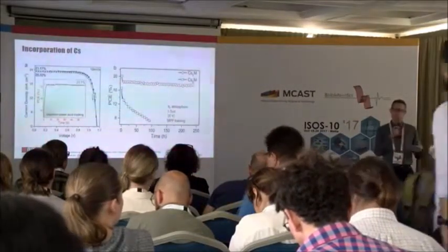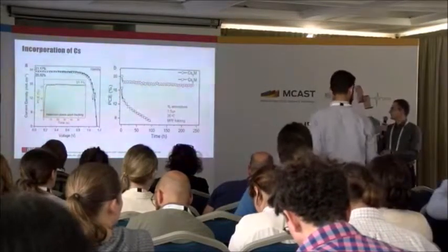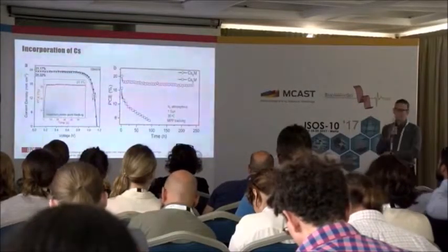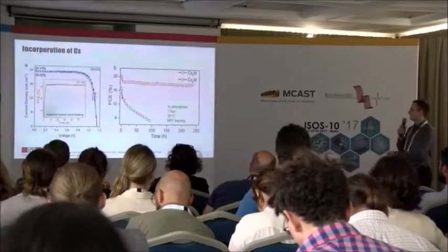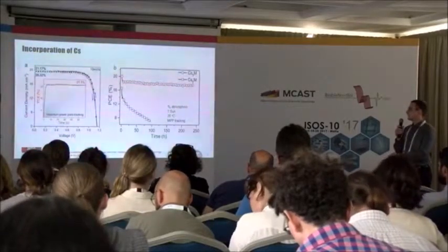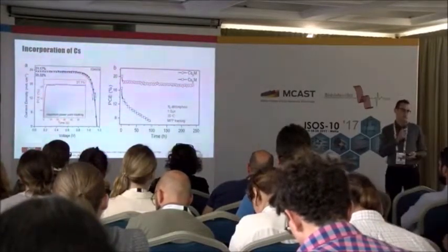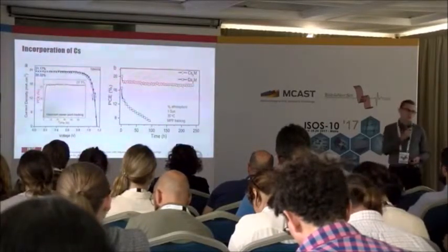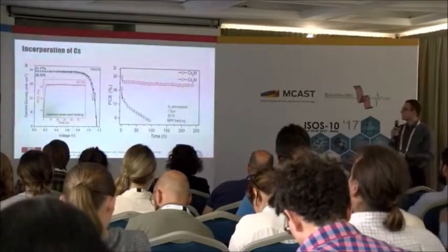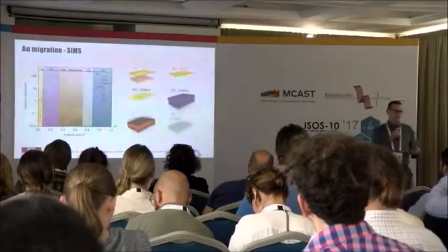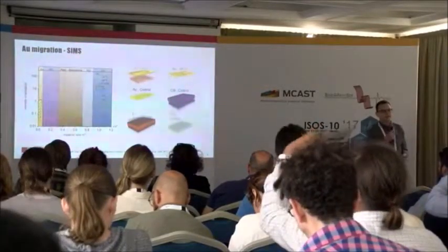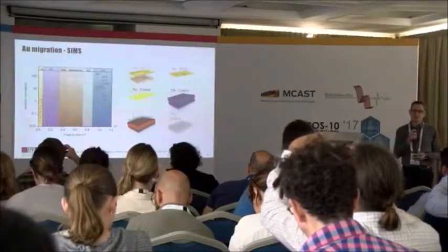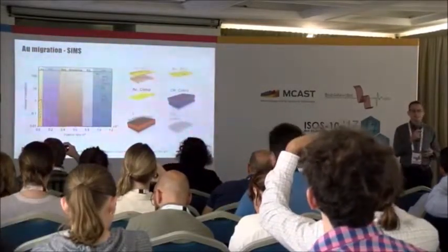So I'm using this composition mostly because we can make them so reproducibly at high efficiencies that it's easy to study stability afterwards. And you can see that without the cesium, the perovskite, under rather gentle conditions, at nitrogen, 20 degrees, is already degrading quite a lot. This is under LED as well. When we add cesium, we can improve this quite critically.